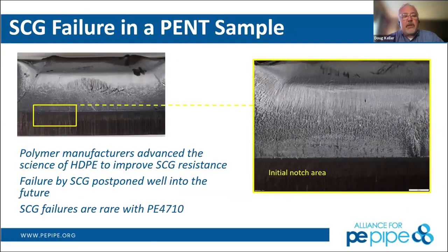So this is just kind of a close-in view of a slow crack growth failure in a PENT sample. The dark area in the right picture is where we said the initial notch is. We put a notch into the pipe, so we're already starting that failure mode. And then we apply a tension to the pipe at elevated temperatures, or to the coupon of material. And so what we're able to see is that we are now pushing well into the future. Initial work on the PENT test said that 1 hour of PENT time is roughly 13 years of lifetime in the ground in a typical environment.